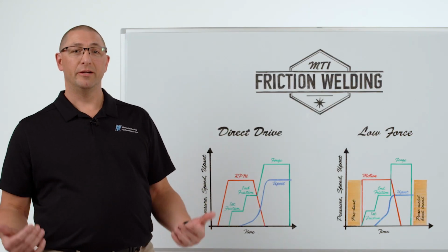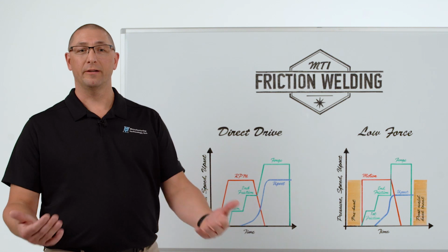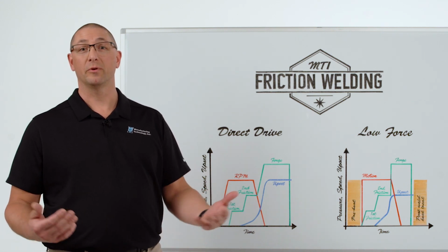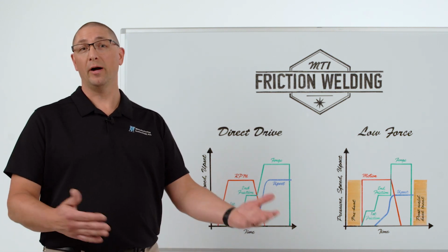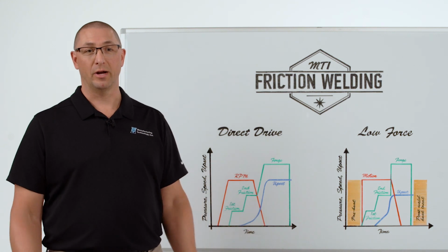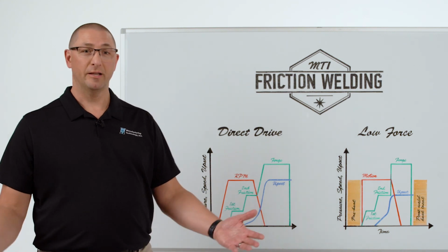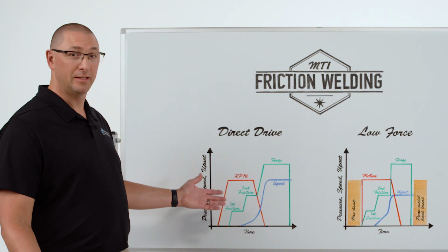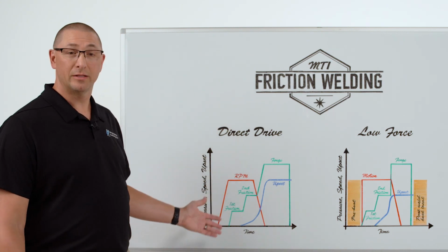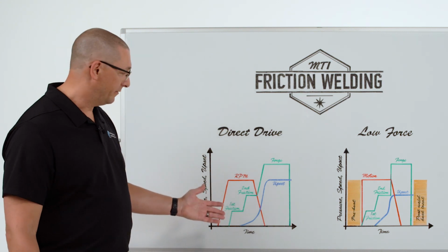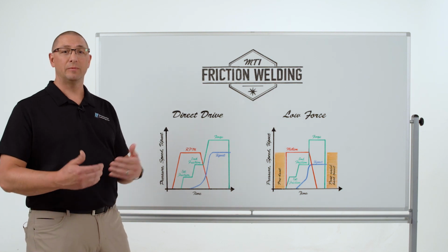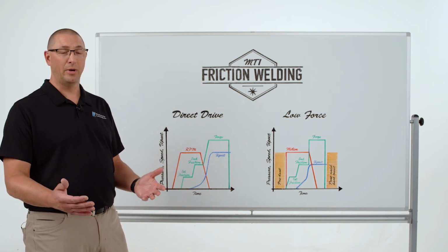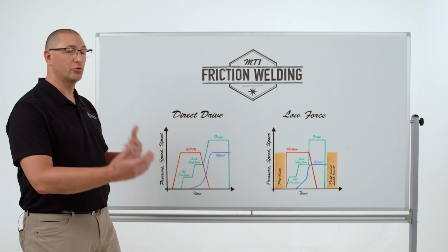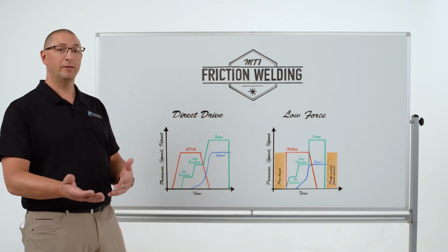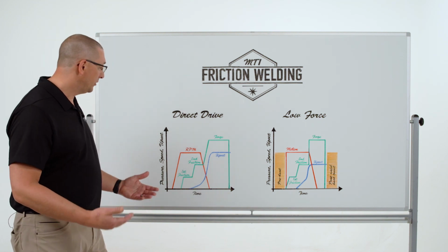Hydraulic cylinder rods are near and dear to MTI's heart because our very first friction welding experience was done with Caterpillar Tractor Company, who we bought the rights and the patents for the inertia welding process from. Piston rods have been done since the mid-1950s, 1960s, and the predominant technology is direct drive. And the reason for that is we need to be able to build enough heat into the component to be able to control the cooling rate and avoid the formation of martensite. So we do that in direct drive.